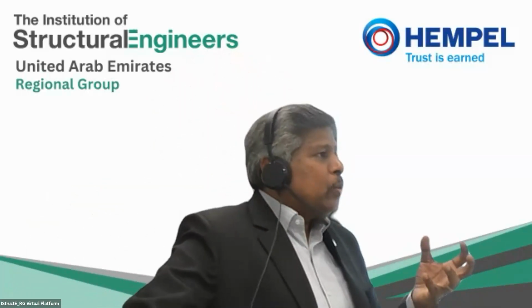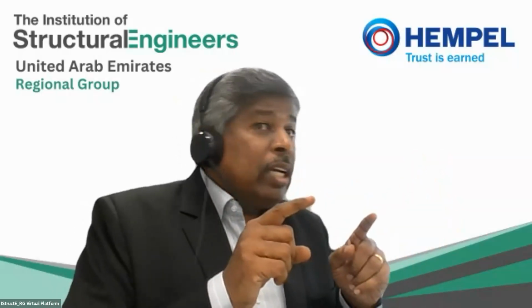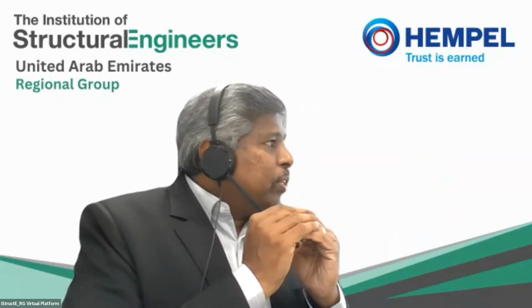I think Declan, that's an important question, because a lot of times when people say I will go for cementitious, I will not go to intumescent, it is primarily because of the cost of the intumescent coating, right? We were just doing some calculation prior to this with Shapur. When a designer works on trying to save cost, they will try to reduce the amount of steel as low as possible. But especially at the time of fire the steel will fail very quickly, so it might make sense if you slightly increase the thickness of the steel, and then reduce the thickness of the coating. Thereby, you get an overall commercially advantageous system, and Hempel can help provide that.